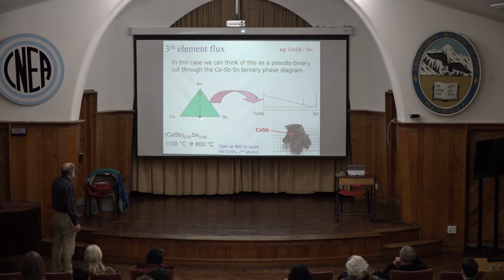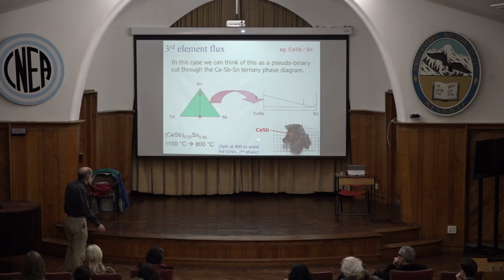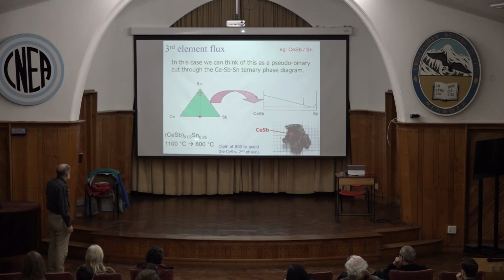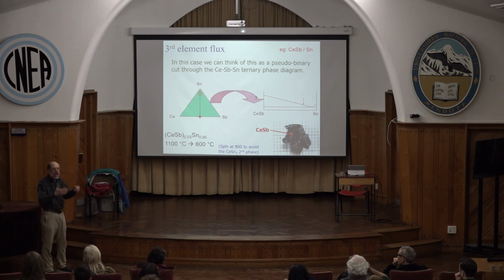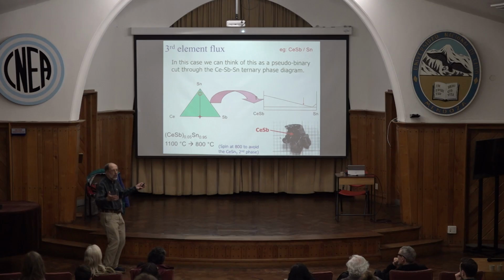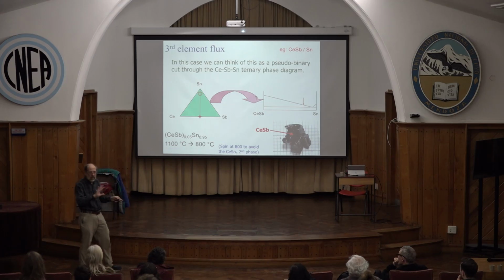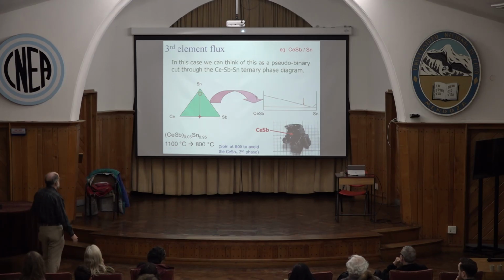So, if we want to put this into the language we've just been discussing, I want to grow cerium antimony. I'm starting with a composition that is super tin rich. I can take this cut, and this is called a pseudo-binary. I've got tin, I've got cerium antimony, and I'm hoping to hit the liquidus line for cerium antimony. And since I'm telling you the story, it obviously works. So if I put in 5% cerium antimony and a lot of tin, heat up to 1100, cool to 800, I can get these beautiful crystals of rock salt cerium monoantimonide. They have super high purity. I get residual resistivity ratios of 700. They are lovely. No tin contamination. You can do lots of good stuff.